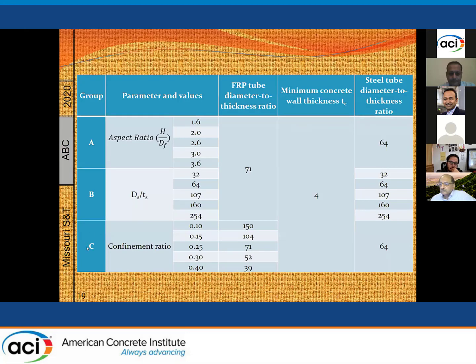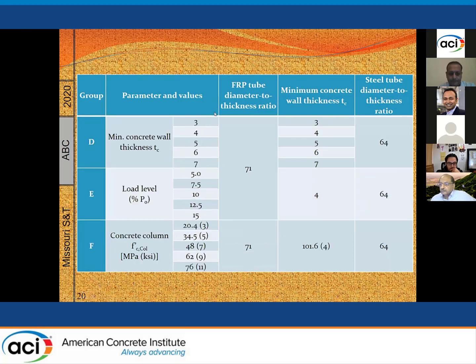In group number C, we looked at the confinement ratio. We looked at different confinement ratios by changing the thickness of the FRP, moving from 0.1 up to 0.4. And then for group number D, we played with the concrete wall thickness, so it ranged from 3 inches to 7 inches.